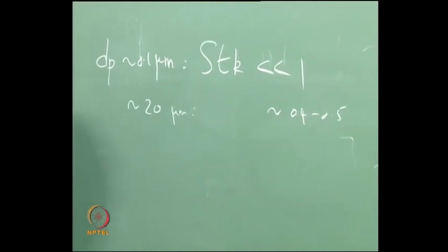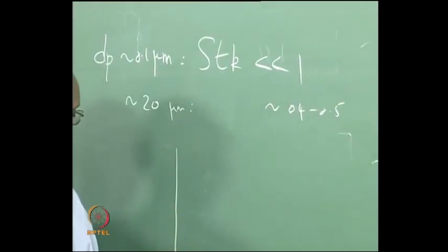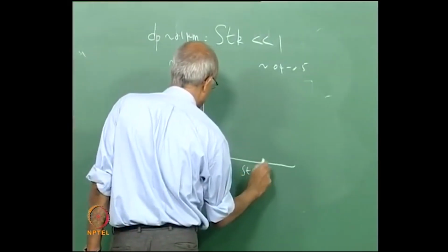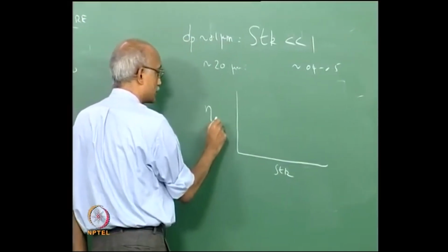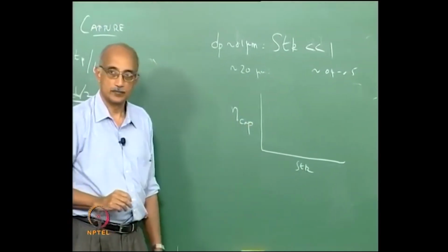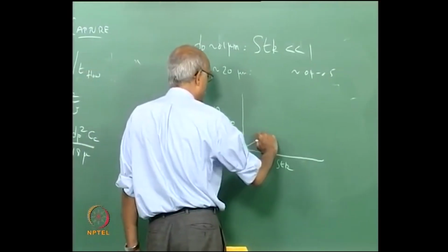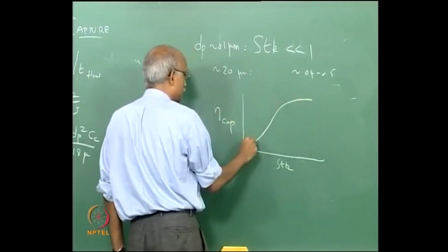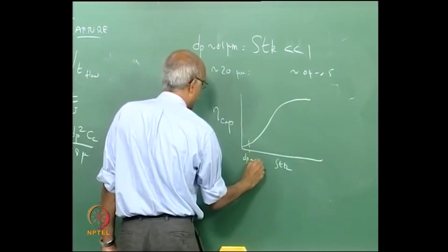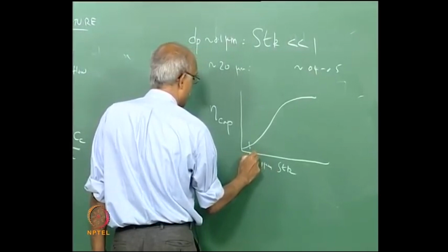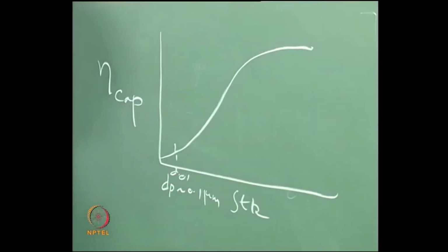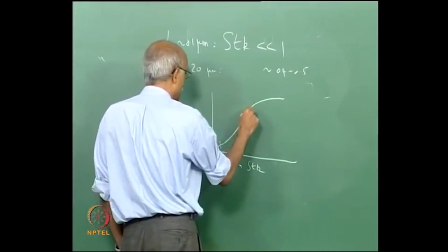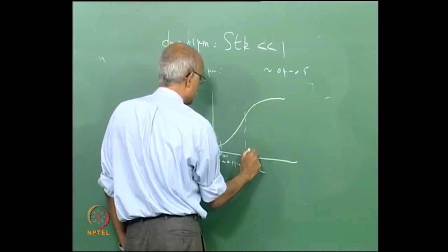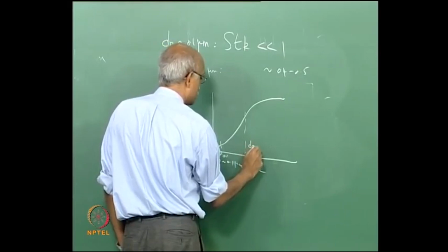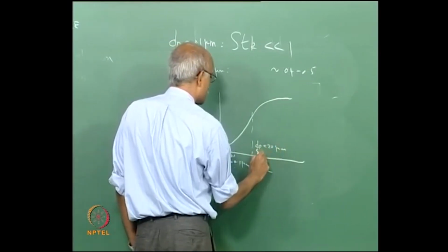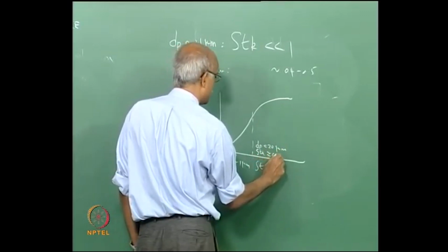So what is the practical implication of that? If you recall the graph we had sketched in the last lecture, if you plot Stokes number versus capture efficiency, you have an S-shaped curve. So for a particle diameter of 0.1 microns, your Stokes number is going to be roughly 0.01, and for a particle of size dp equals 20 microns, Stokes number is going to be approximately 0.5.